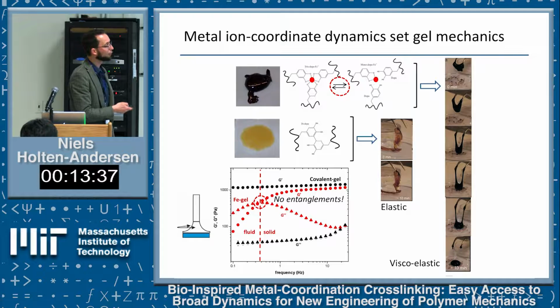If it's a little piece of rubber, the material doesn't really care how fast or slow you deform it. It behaves the same way. So you get two types of elastic measurements out of it: the storage modulus, and the loss modulus, which is G double prime. This is the direct elastic response of the network, and the other is the fluid-like response.